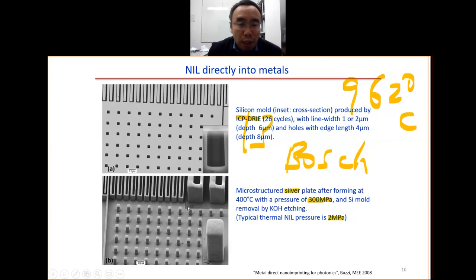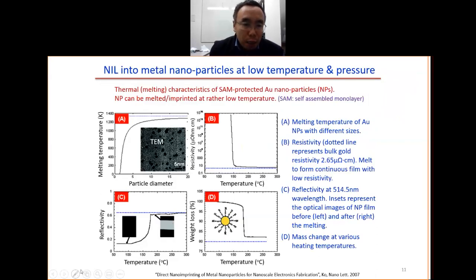This is the demonstration to show that it is possible to do the imprint into the metal, but you need either very high temperature or very high pressure. So that is not easy. In this example here, we use metal nanoparticles. For the case of gold, the melting point is a little bit higher, 1,000 degrees. But with gold nanoparticles, for example a gold nanoparticle of maybe 2 nanometers, the melting temperature is much lower. In this example here, you get a 150 degree melting temperature.